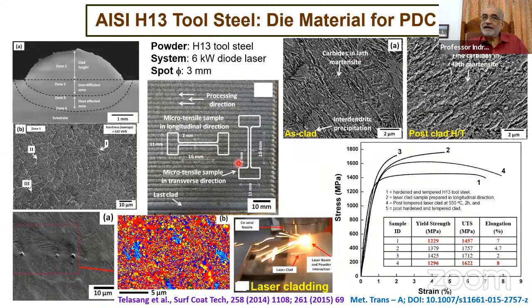So here we don't have a lot of retained austenite. Instead, we actually have more volume fraction of martensite than the original component. And why is it so? So you are solidifying steel from molten state all the way to room temperature. And during that, because of high hardenability, the steel not only solidifies into austenite, but also undergoes austenite to martensitic transformation during the same continuous cooling process.